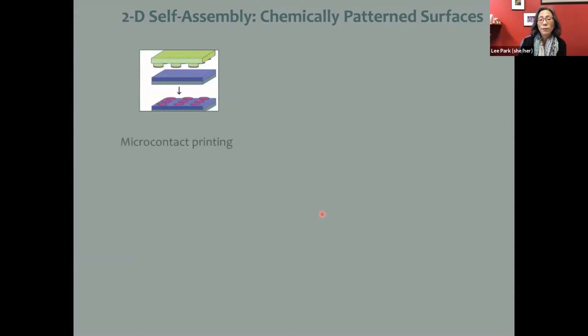And we have a couple of options for doing that. So one option is what's called microcontact printing. This is the same thing as taking a rubber stamp, inking it, and printing that onto a piece of paper. The differences are that the ink you're using is not chosen for its color, but for its molecular properties. So you're inking your stamp with a molecular ink that's one of these amphiphilic molecules, and you are stamping it onto a surface so that you can chemically pattern a surface so that you'll have regions that are hydrophilic, regions that are hydrophobic.